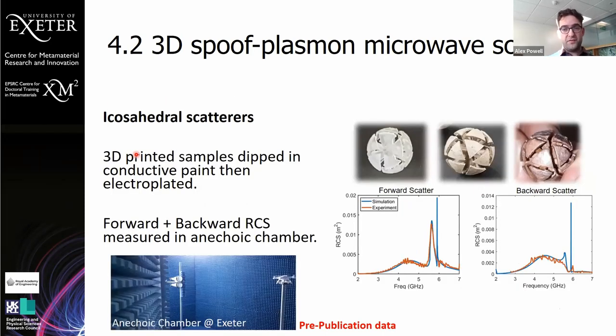And so I've 3D printed some of these. Again, this is done by photopolymerization and then dip coating and then electroplating. And we placed them in our anechoic chamber and measured the RCS both in the reverse direction and in the forward direction. The samples will be placed where this drone currently is in this picture. And we get pretty good agreement between theory and experiment here.